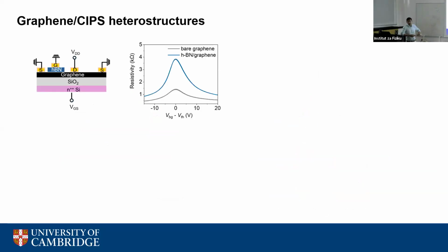To understand what happens, first we made a very standard FET. So let me explain this device. What we have here is a graphene transistor with a silicon oxide backgate. So this is a very standard graphene transistor. And we want to use this graphene transistor to sense what happens when you put something on top of it. So we first put an HBN, which is an insulator. We know that it does nothing other than just being a dielectric.